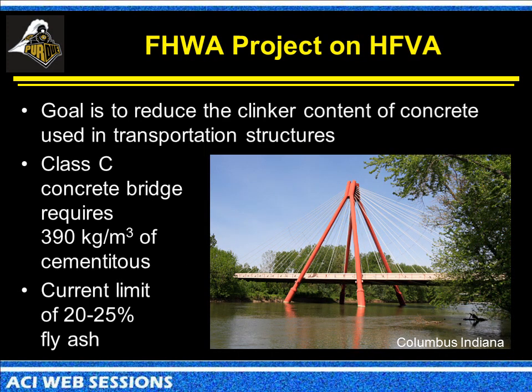The whole idea of this project is really to look at reducing the amount of clinker content per cubic meter of concrete. So for a typical bridge deck, we're looking at something around 390 kilograms per cubic meter of cementitious materials. And right now, the limits in many of the states are between 20-25% fly ash in those ranges.